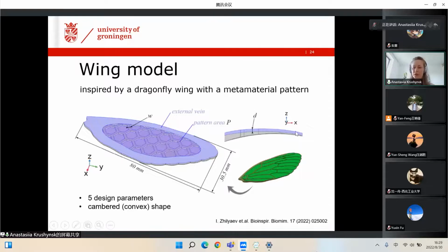And you can see here two important things. So first, our wing is not flat. So it's cambered or convex. And this is on purpose. So first of all, this is because natural wing is not flat. Second, because having non-flat wings provides some benefits in terms of modeling. I will explain you this later. And second, you can see that we have the metamaterial pattern only on the top surface of the wing, not below. This is for simplicity. So in this model, we end up having 5 design parameters. This is the pattern area for the wing pattern, so this is P. Then out of plane and in plane stiffness of the elements. And also to have a little bit more design freedom, we introduced the so-called scaling parameters along the X and Y axis to be able to make this pattern anisotropic.